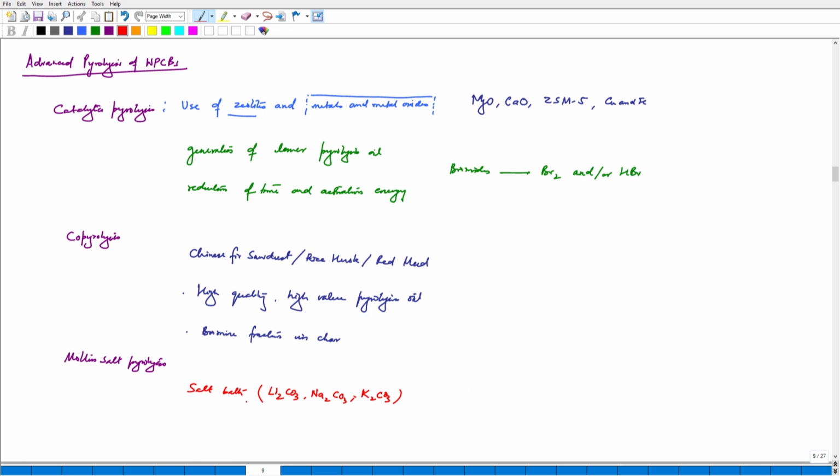If this bath is used, we can also have an advantage of bromine conversion, 99% bromine in salt bath, and basically it leads to alkali metal bromides, and we have recovery of 95% copper. So metal recovery is also described.